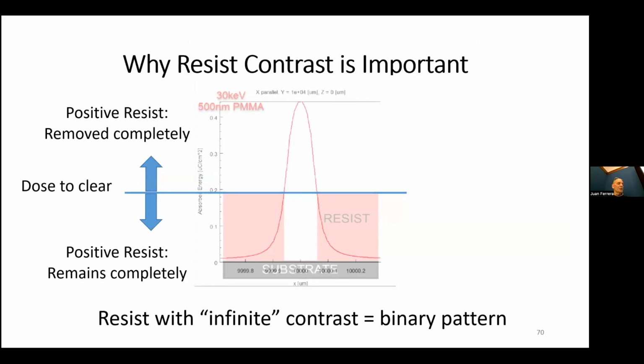So what we'd like to have are resists with really good contrast. And the reason we want resist with really good contrast is we either want resist or we don't want resist. We don't want some sloping resist typically. So this is a plot that tries to show that. And the idea here is we have a representation of our Gaussian beam. And then we have this line here of the dose to clear. So this is the absorbed energy in the substrate versus distance. So what we'd like to have is this to be a very fine line, and either it exposes the resist and it's all gone when we develop, or it doesn't expose the resist and it all stays. Now that doesn't happen exactly, but we'd like to get as close as we can.